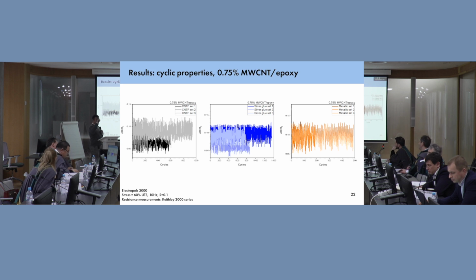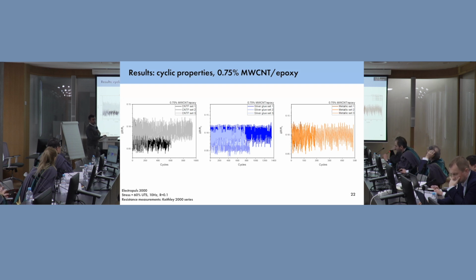We can still monitor the rest. We still have a reading because it didn't break here. Maybe we were unlucky in this, or maybe we were lucky. In either case, generally with cyclic testing, we have SN curves or graphs, sorry, where we plot the number of cycles and the stress. And you have your groups of data to formulate what exactly is the point of breakage. The data set is small. I won't say that this is exact confirmation that the CNTFs last more cycles. At the exact point where our data ends, it's where we see sample fracture take place, and we stop it at that point. Perhaps they can last a bit longer, but it's not comparable. Thank you, Professor.